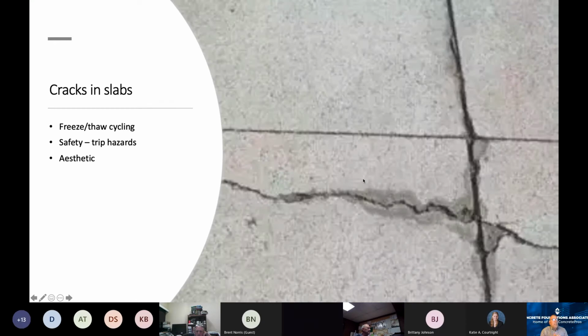Here's a crack in a slab. And I've enlarged this to really look at the crack itself. And you can see the joint cuts by the contractor. And as nice a job, although that's pretty messy, the slab joint that's going vertical there is kind of unraveled. The timing was a little late on that crack, but the horizontal one's really nice. And yet, as nice as that horizontal crack is, look at what the concrete decided to do. So what does that tell you? It tells me, first of all, that they didn't go deep enough with their slab joint. And you can kind of tell that based on the dimension of that horizontal joint.